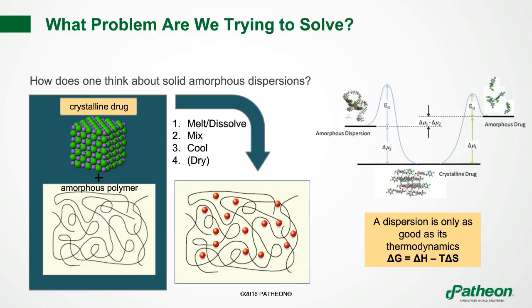On this slide, we typically get a crystalline drug, poorly soluble, and to increase the solubility of this, we want to mix it with an amorphous polymer. This can be done by co-mixing or dissolving in a solvent, hot melt extrusion, or spray drying. Ultimately, what we want is an amorphous dispersion where you have the drug molecules, in red, molecularly dispersed in the polymer.